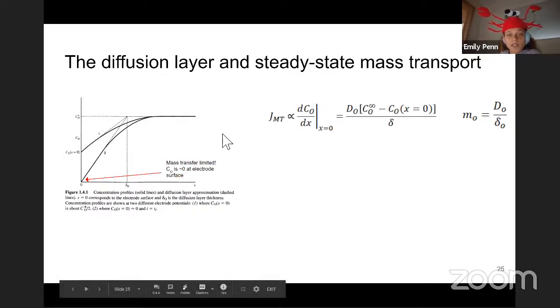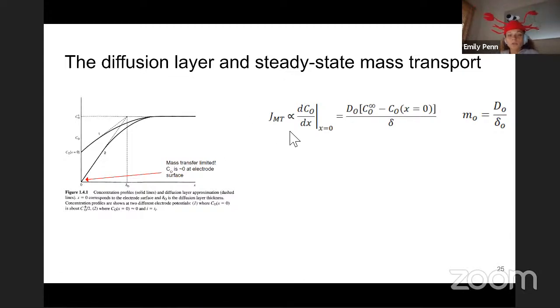So thinking about these steady state mass transport methods, we can again look at Fick's first law, which we talked about before, where the flux of a species is related to the concentration gradient at the electrode surface at x equals 0. If we're talking about a mass transport limiting case, we again want to say that the concentration is 0 at the electrode surface. So our concentration gradient will be the bulk concentration minus the concentration at the electrode surface over this delta, where delta is our diffusion layer thickness. So that's this region here where we're going from the bulk concentration to the electrode surface.